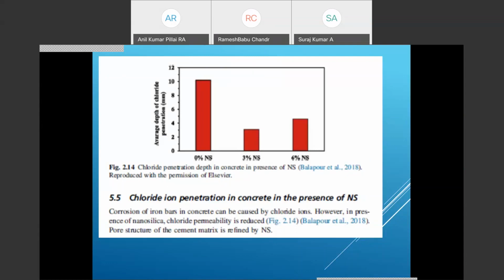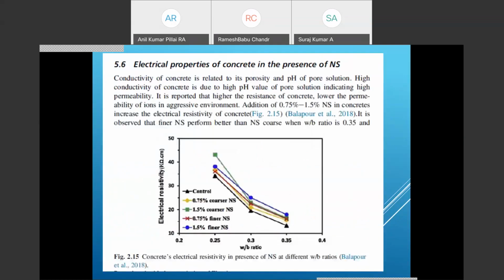Pore structure of the cement matrix is refined by nano silica. Electrical properties of concrete in presence of nanosilica. The conductivity of the concrete is related to porosity and high pH content. So when you use nanosilica, it has been observed that the concrete produced has higher resistance to electricity and lower permeability of ions in aggressive environment. 0.75% to 1.5% of nanosilica increase the electrical resistivity of concrete.